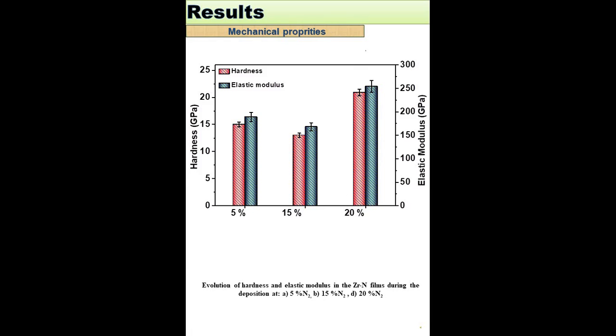The nano-indentation test of the zirconium nitride thin films showed that the hardness and elastic modulus revealed a modification as a function of nitrogen flow rate, where the best value of about 22 gigapascal was obtained at 20% nitrogen flow rate.